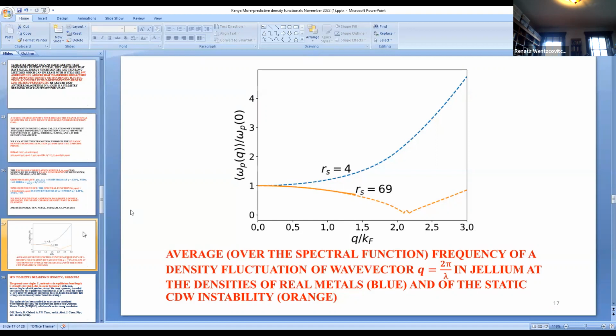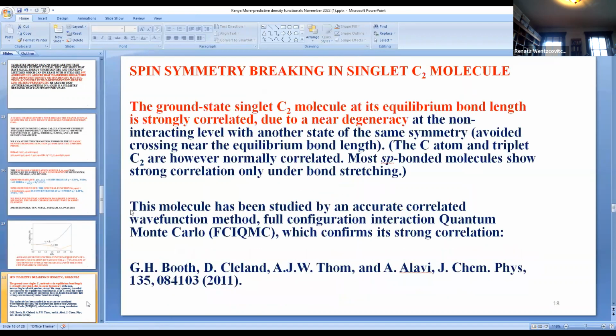When we get to low density, like RS equals 69, the plasmon frequency disperses the other way—downward. At some point, the plasmon disappears as a collective excitation because it can break up into a particle-hole pair, roughly at Q over Kf equals 1.5. But we can continue with the dashed line by averaging over the spectral function to extract the frequency, and we'll see this quantity drops to zero frequency at Q over Kf equals 2.28, then comes back up again. There's a critical point where the charge density wave appears, and it appears exactly where it should.